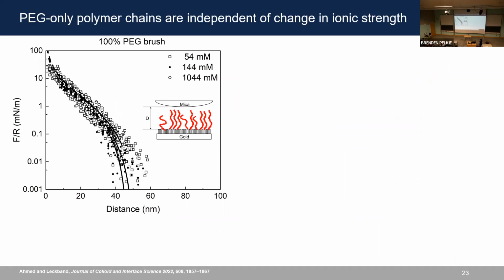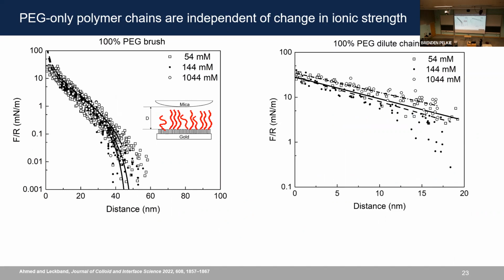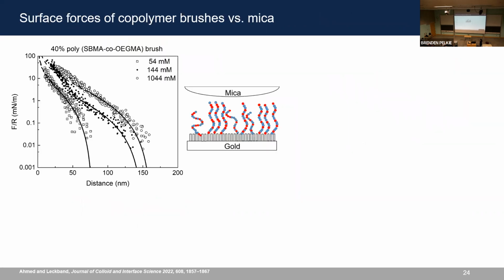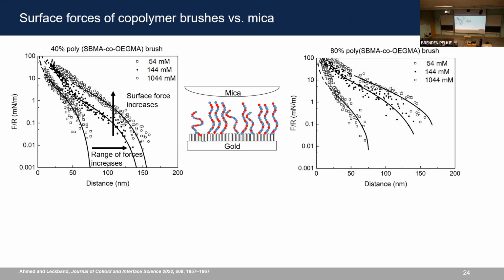So first, with PEG-only polymer chains with no zwitterionic component, we see that the force distance profiles for both high and low density polymers overlap each other. So there is no ionic strength dependent behavior, and that's not surprising. On the other hand, if you look at the 40% sulfobutane content in the statistical copolymer, we see that both the range of forces as well as the surface force measured at a certain separation distance increase. And this difference is more apparent when you go up to 80% sulfobutane content in the copolymer.